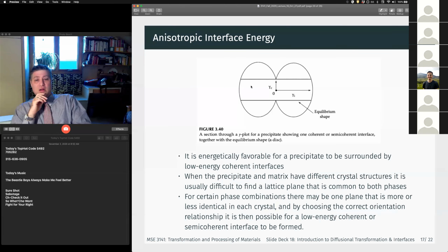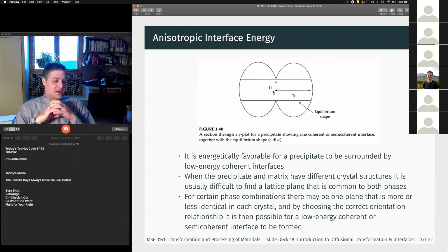So the interfacial energy is going to help determine the equilibrium shape. It's a little counterintuitive sometimes when people think about this at first, because we end up with a lot more interfacial area when we have a non-spherical shape. But what we're trying to minimize is the overall energy. So if by making a sphere, we make a large fraction of that interfacial area be a high energy configuration, if we squish it down into a plate, then we can reduce the overall energy.